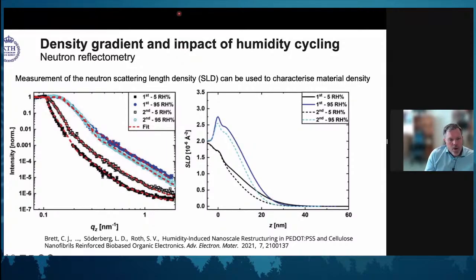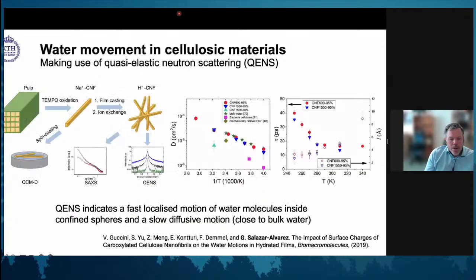And then you can start to think about why we use neutrons and water. Yes, we want to understand the structural changes. I want to point out, for anyone interested, there is what I believe is an excellent paper, made quite recently, that is starting to look at something called quasi-elastic neutron scattering. It is a more advanced technique and needs more material. You can't do this on a thin film, but you can use quasi-elastic neutron scattering to study the diffusion of water in a material. They have done this for different types of CNF and bacterial cellulose, so you can start to understand how water diffuses in cellulosic materials.